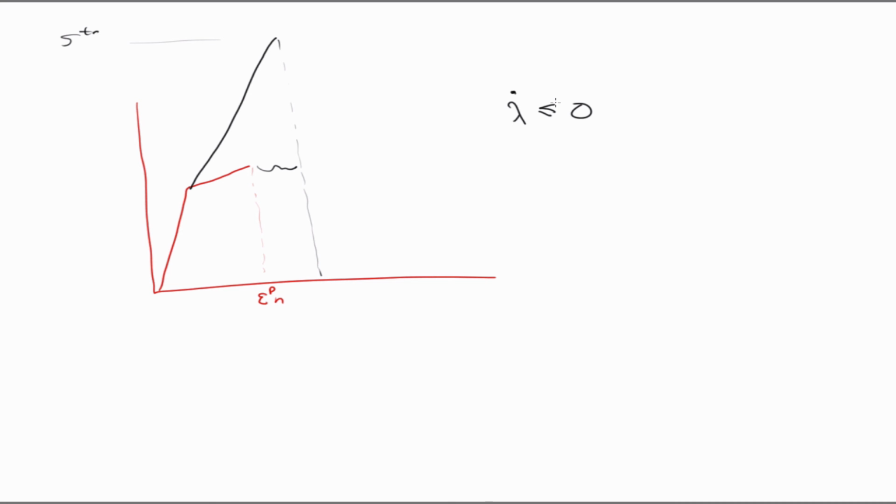I think what he's saying is, in the if statement to check whether we are plastic or not, anything that exceeds this value, I'm going to treat it like it's plastic and move forward. In this case, you're always monotonically loading, so you are going to be up here. Had it been unloading, you'd compute a negative delta lambda, which can't be, and then you discard that solution and accept it as elastic.